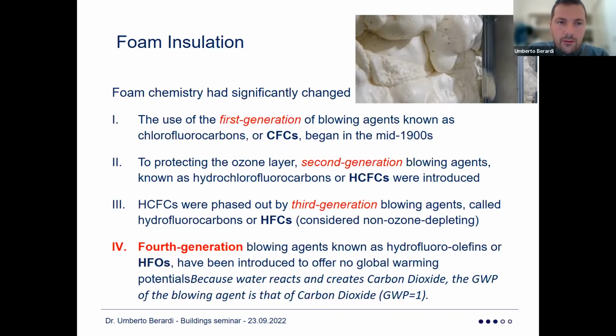We made sure that, from using chlorofluorocarbon to expand the foam, we started using hydrochlorofluorocarbon. So HCFCs are the blowing agents typically used in the second generation, 15 years ago. Now, about 10 years ago, in an effort to protect the ozone layer even more, we went to a no ozone depleting gas at all. So we moved to hydrofluorocarbons, HFCs, which are still the standard third generation blowing agent. What we've been working on in my lab is moving towards the fourth generation of blowing agents. These are blowing agents that have not only no ozone depleting power, but also a global warming potential of 1, because at the end of the day, they use carbon dioxide to blow the foam.